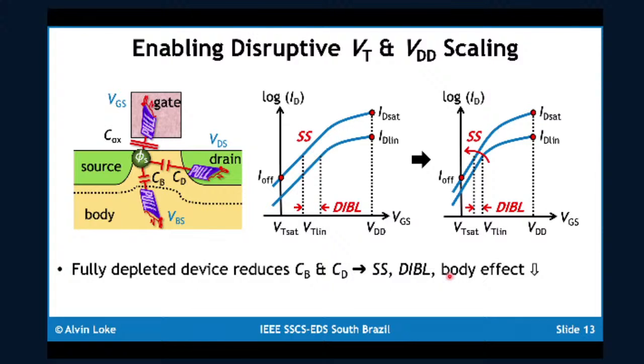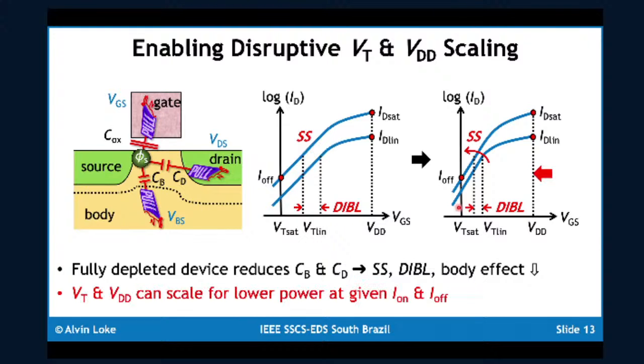And by being able to reduce the threshold voltage, if you preserve the same overdrive for the same performance, essentially what you can do is bring the supply voltage and threshold voltages down while still preserving the same off and on current, which is a thing of beauty, obviously. Just to put some numbers to this, at room temperature, in the last planar nodes, we were seeing subthreshold swings as high as about 120 millivolts per decade.